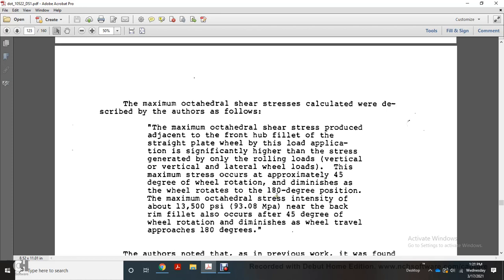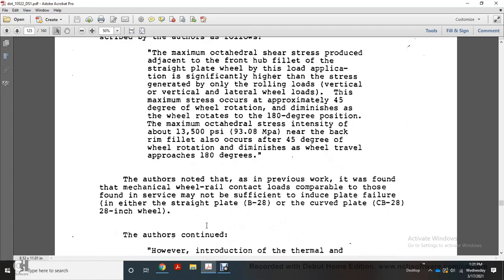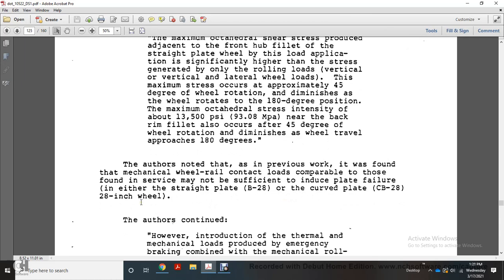Maximum octahedral stress intensity of 13,500 pounds near the back of the rim fillet with a curve at 45-degree angle with the wheel rotation diminished as wheel travel approaches 180 degrees. The author noted that previous work found mechanical wheel-rail contact loads comparable to those found in service may not be sufficient to induce plate failure with either the straight plate, the curved plate, or the 28-inch wheel.